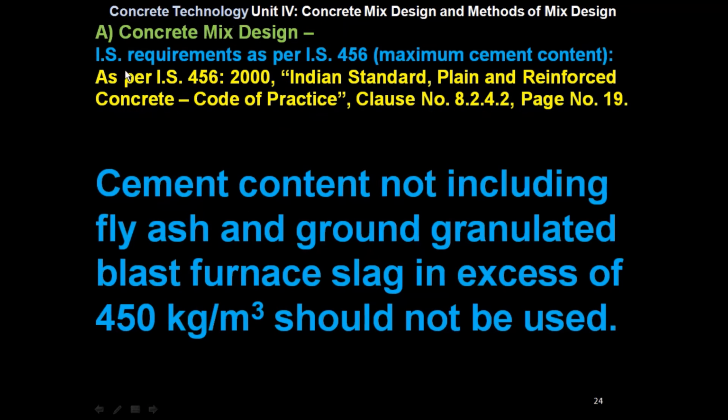IS requirement as per IS 456, maximum cement content. As per IS 456-2000 Indian Standard Plain and Reinforced Concrete Code of Practice, clause number 8.2.4.2, page number 19, cement content not including fly ash and ground granulated blast furnace slag in excess of 450 kg per meter cube should not be used.